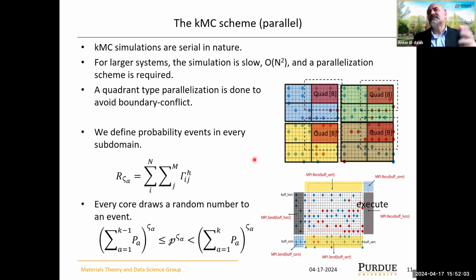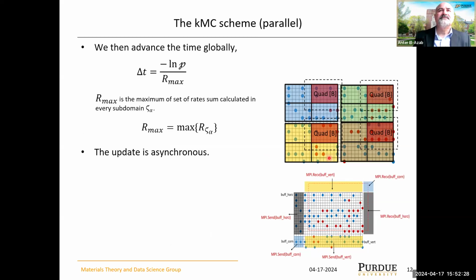That enables you to simulate larger areas on the surface, and that is important because the time it takes for Monte Carlo to execute can be a limiting factor in studying the system size, and the system size has to be dictated by the fact that you need to resolve certain microstructure features like we have in our case.